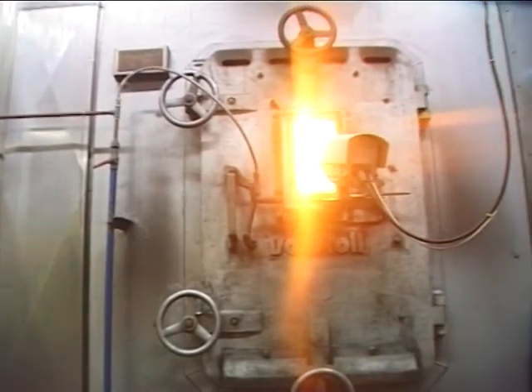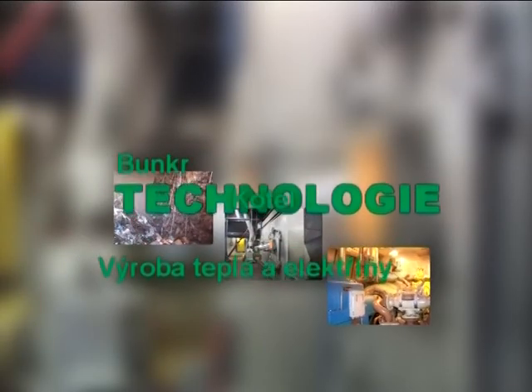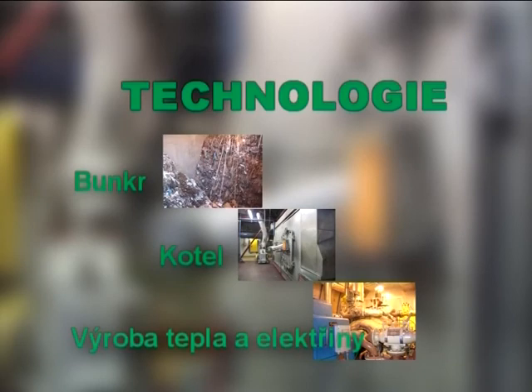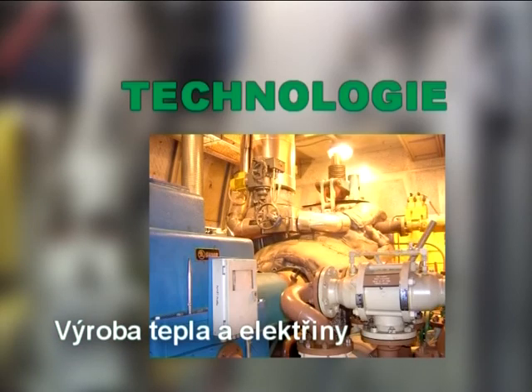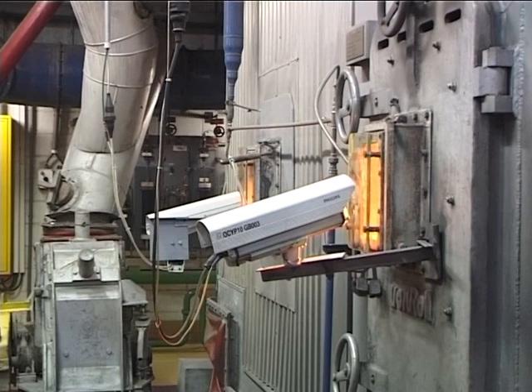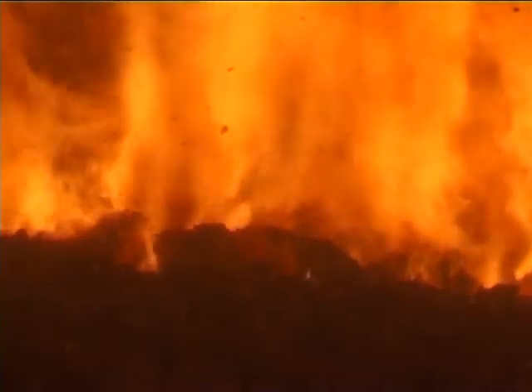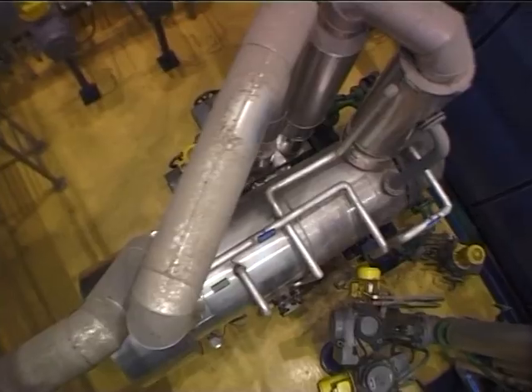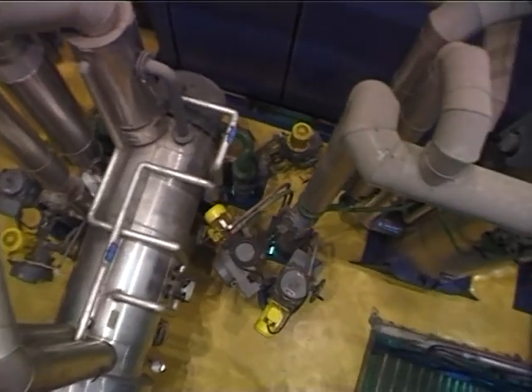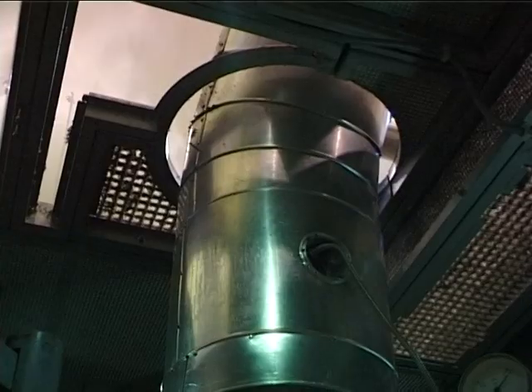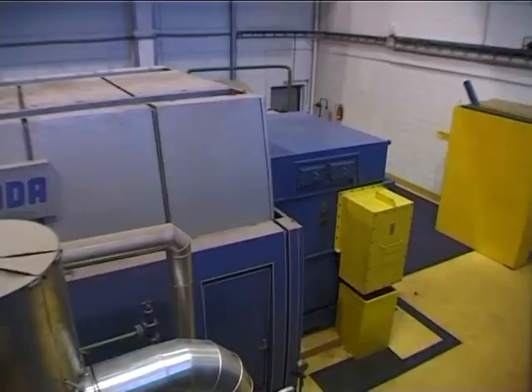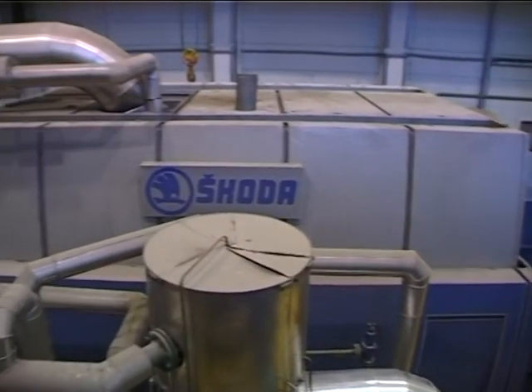In the burning out zone beyond the combustion chamber, where combustion products remain for 2 seconds, the temperature is between 850 and 1100 degrees C. Energy released during waste combustion is collected in the form of heat and transmitted to the production of steam. The rated performance of steam in the furnace is 43 tons per hour. The steam has a temperature of 400 degrees C and a pressure of 40 bar.